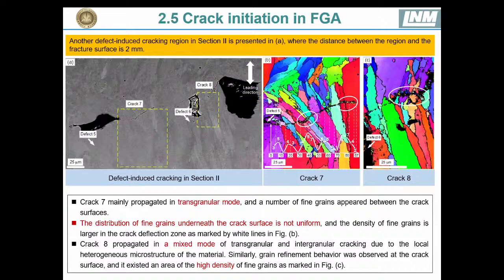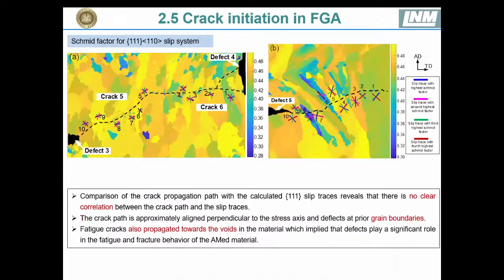And also in this pore, we show that there are also some fine grains around the cracks. It shows the fine grains have a higher local distribution in the marked area. And crack 8 is a mixed mode of transgranular and intergranular cracking due to the local stress distributions.